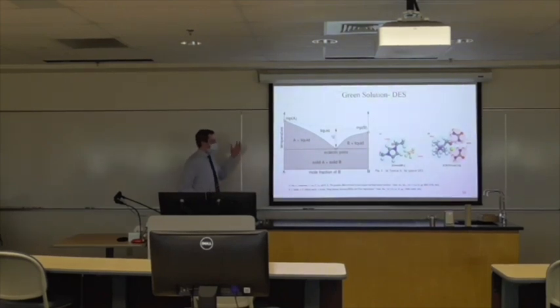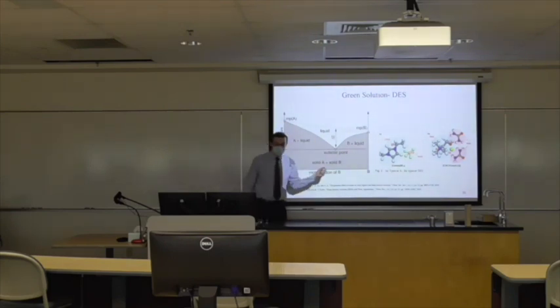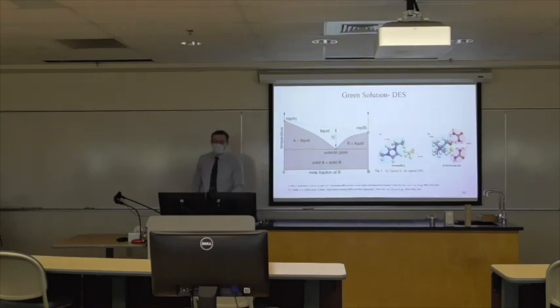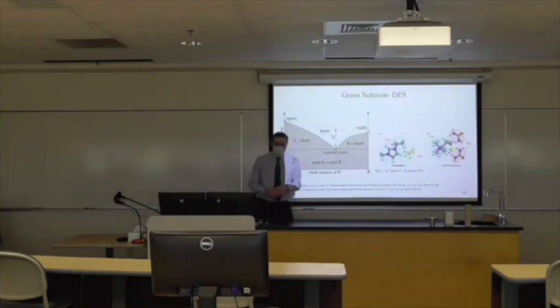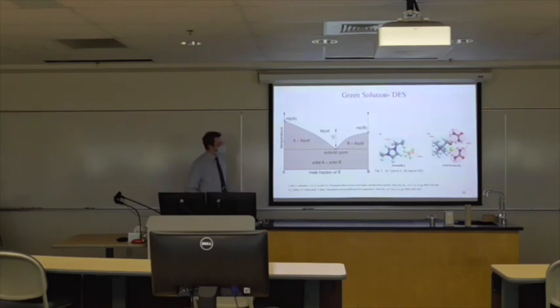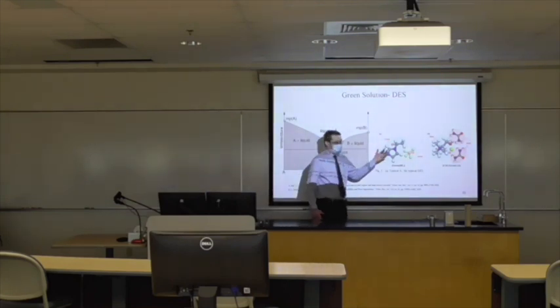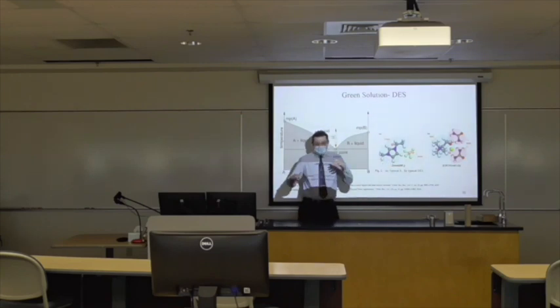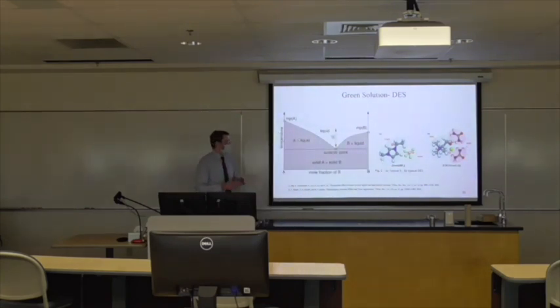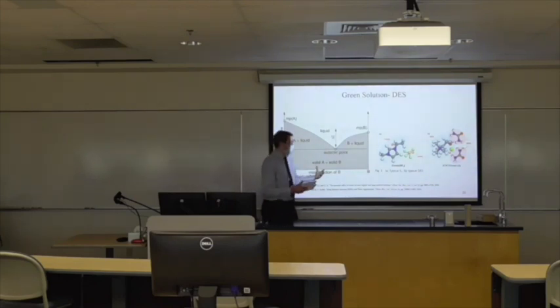So, how a deep eutectic solvent works is that you combine two things together that have their various melting points, and then combine them in the correct ratios. The melting point of the mixture is significantly lower than the melting point of either substance you use. Now these deep eutectic solvents have properties similar to ionic liquids, but have some key differences as well. One of those differences is that ionic liquids always have discrete ions, all the time. They have the cations and anions, and that's how the ionic liquid works.